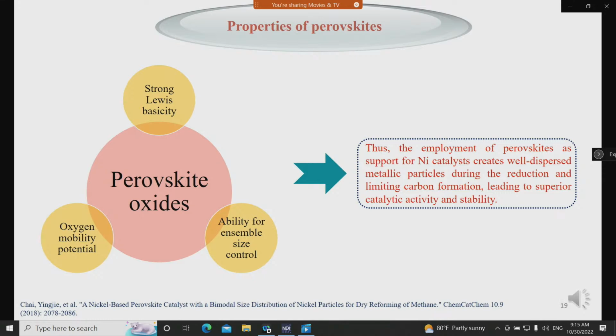The main special properties of perovskite oxide are observed. Perovskite oxides are strong Lewis bases, hence limiting carbon deposition on the catalyst. Moreover, perovskite-type oxides have the potential for ensemble size control, enhancing nickel dispersion, and hence the number of active sites. Also, these catalysts have unique redox properties and remarkable oxygen storage and release capacities, which could promote the oxygen transfer and accelerate the elimination of carbon deposits.